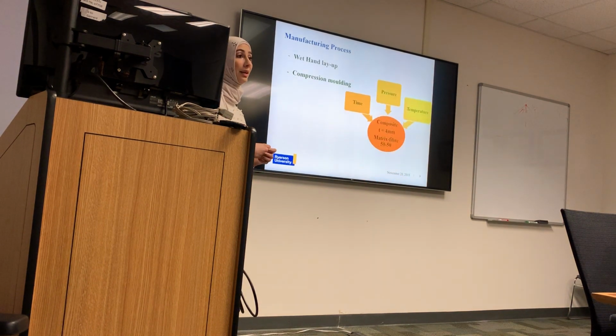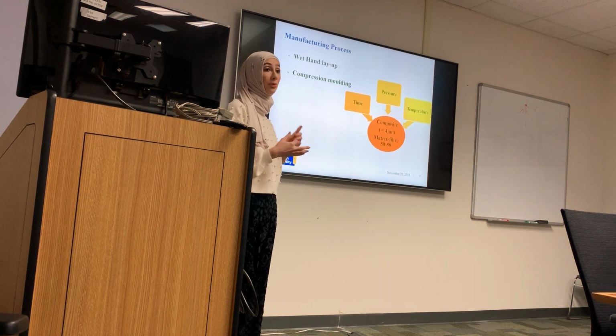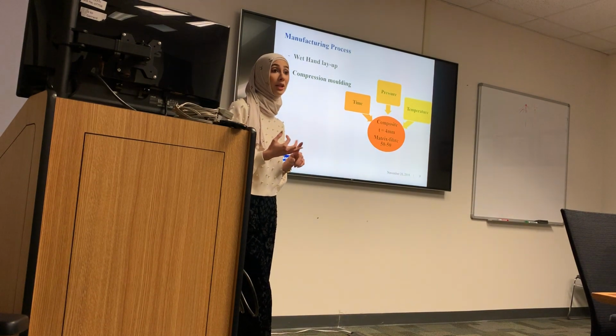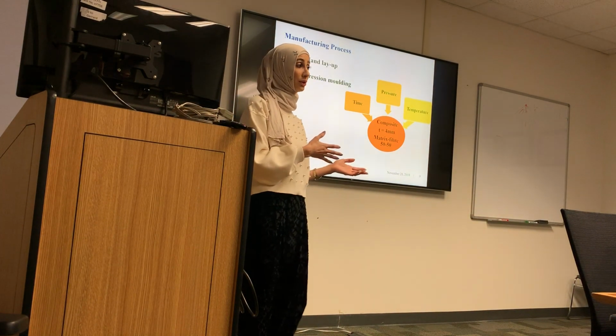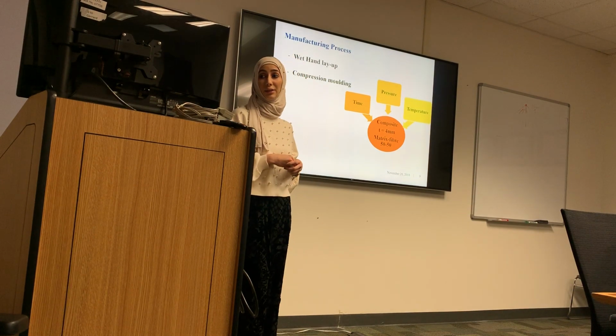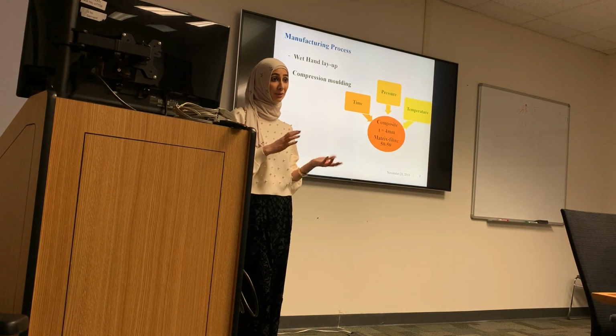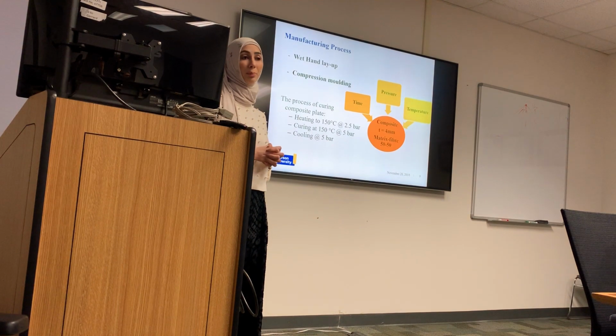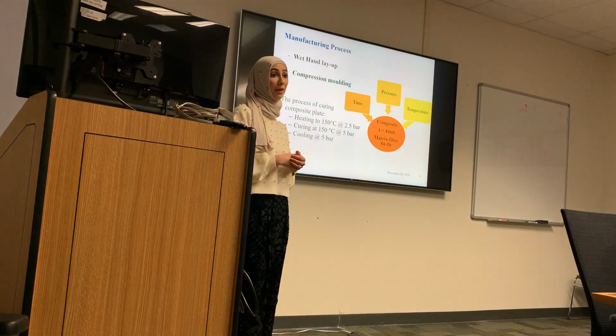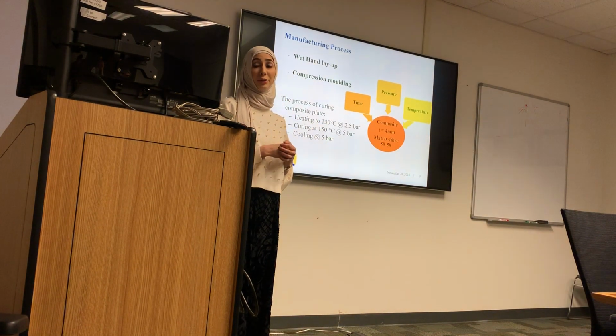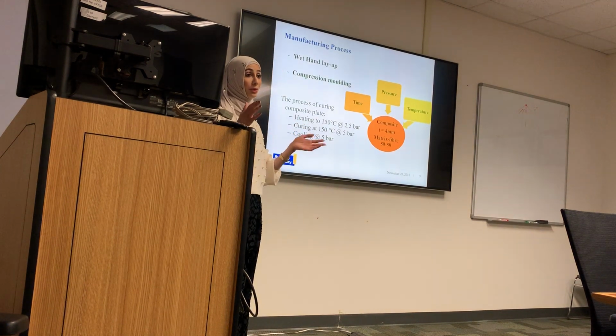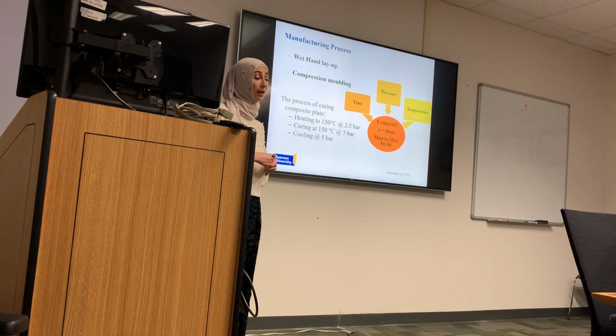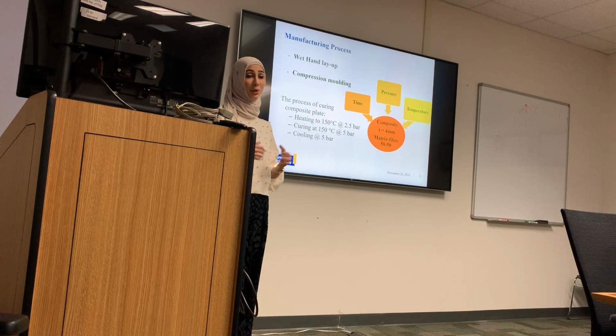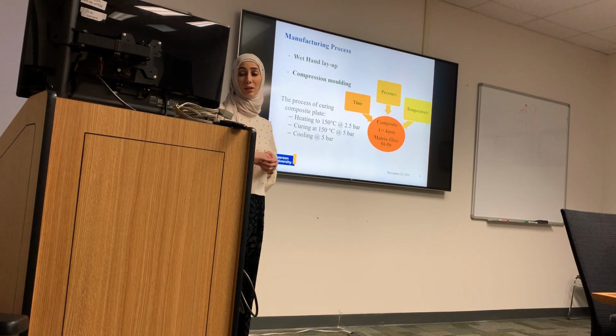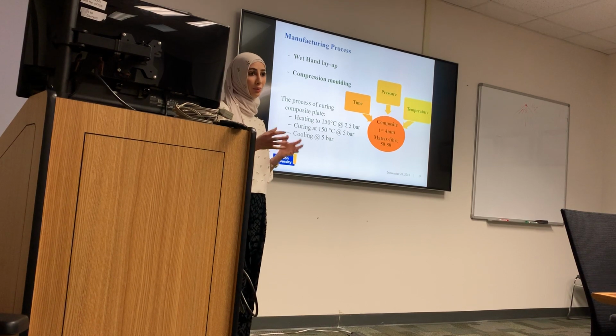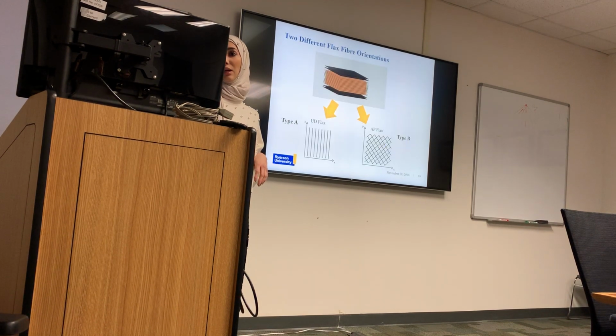The compression molding technique was controlled by 3 main parameters: time, pressure, and temperature, in order to produce a composite with 4 millimeter thickness and a fiber to matrix volume fraction of 50-50. The curing cycle took heating up the composite to 150 Celsius under 2.5 bar, and then curing it for 2.5 hours at 150 Celsius, then cooling it down to room temperature at 5 bar, which is 0.5 megapascal.